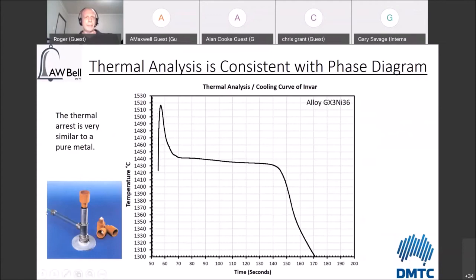So what you're seeing here is a thermal analysis rig from Heraeus Electro-Nite. That only cost you about $200 or so. You can get set up to do thermal analysis of steel for under $1,000. All you need is a data logger and a thermal analysis rig. These setups are absolutely fantastic. If you are casting steel or anything high temperature and you are not doing thermal analysis, you absolutely should be. It costs you about $2 a cup, and the amount of information you get out of it is absolutely extraordinary.